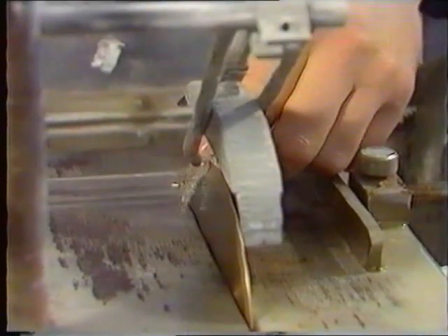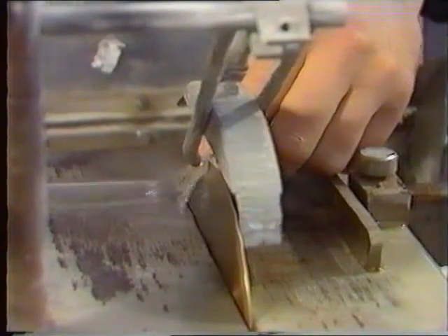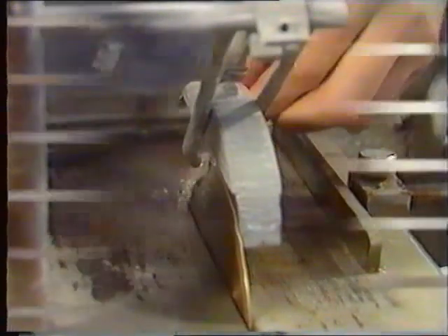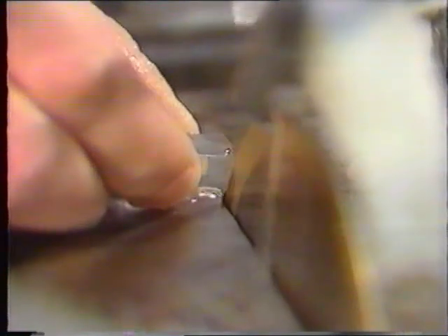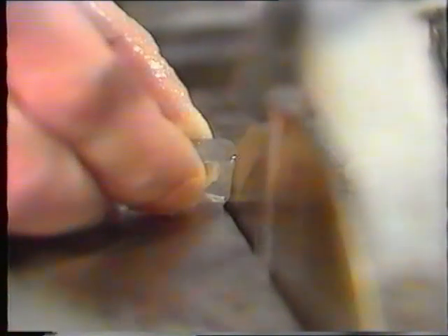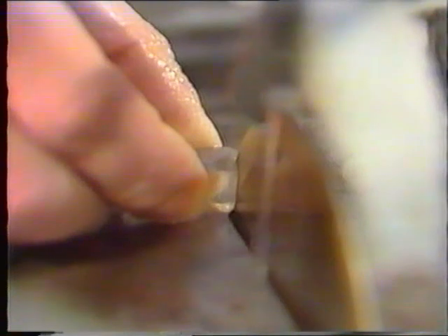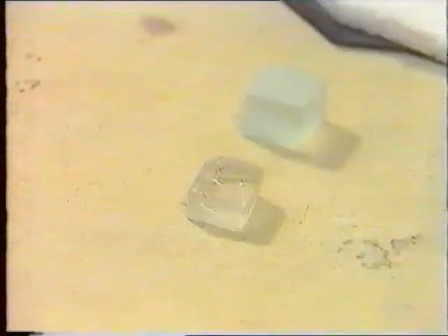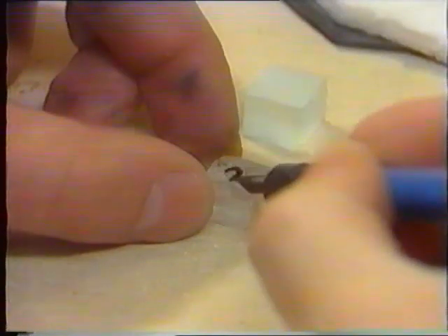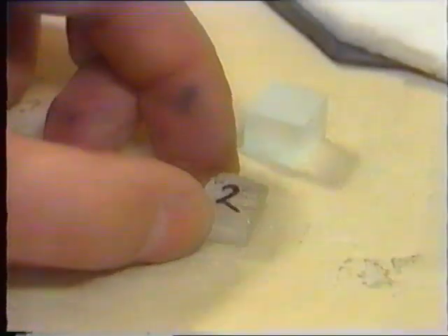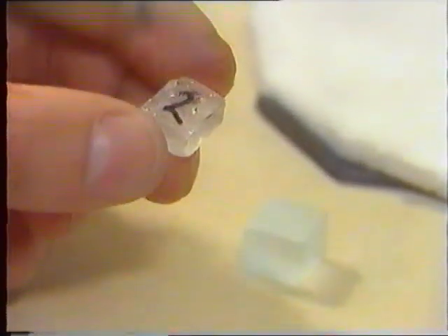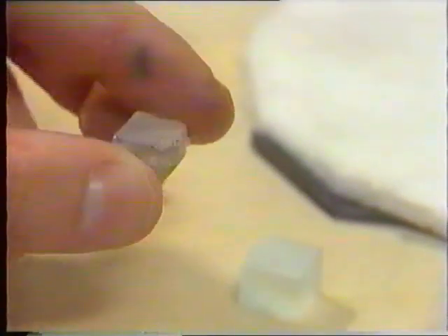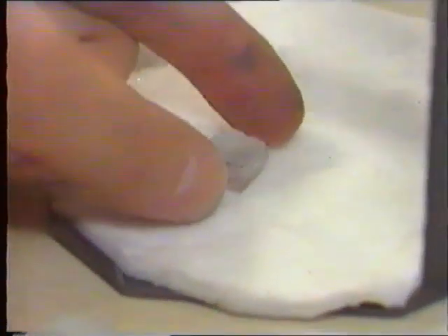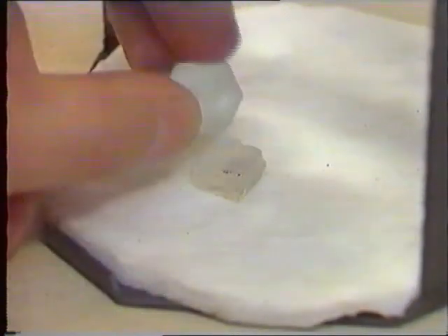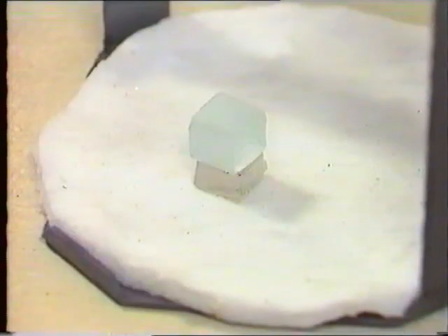This cube is first cooled and then sawn to size. From the face that will be contiguous to the standard glass, about 1 mm is ground off. The opposite face is used for the glass ink mark. The cubic sample of production glass is placed on a holder, numbered face down, and a piece of standard glass is placed on top of it.